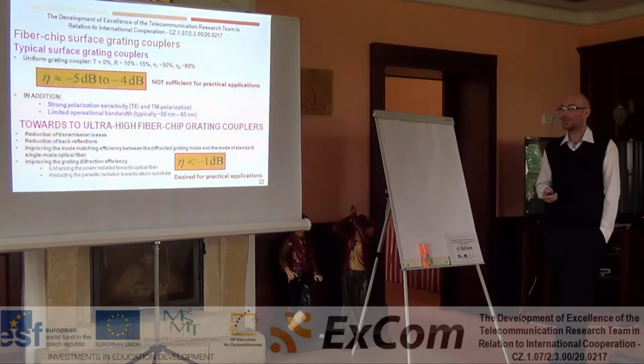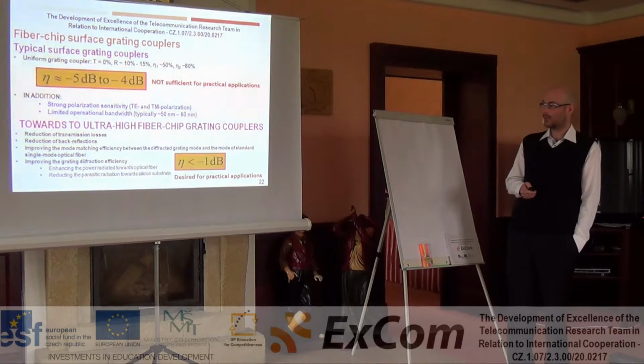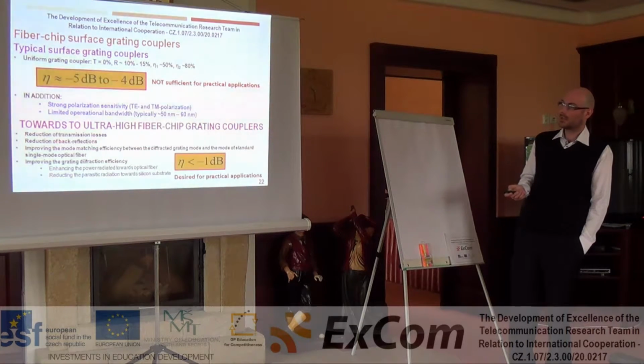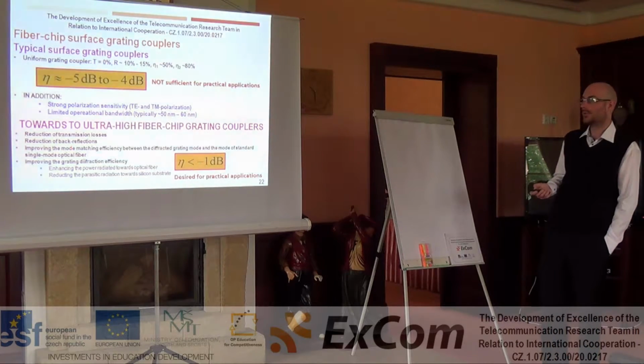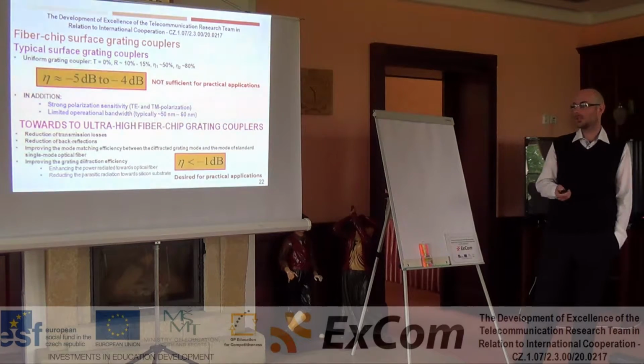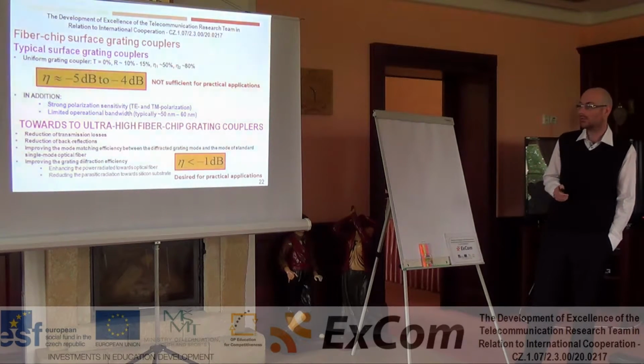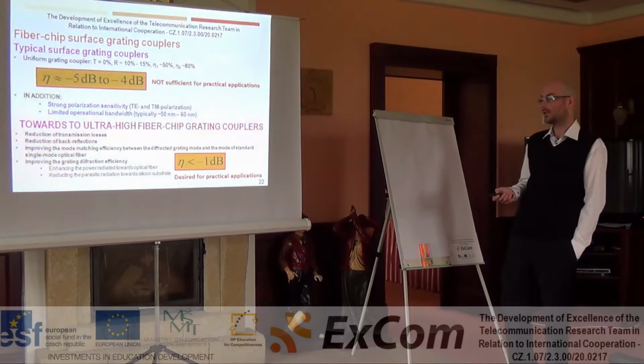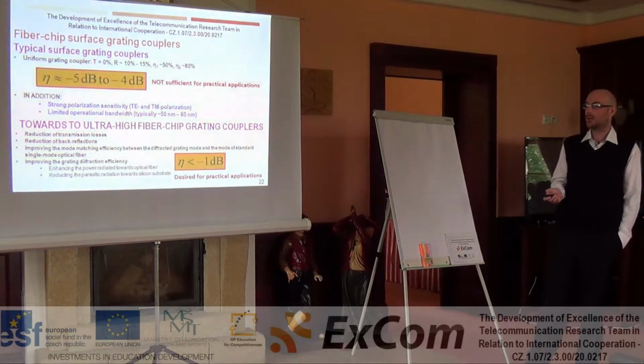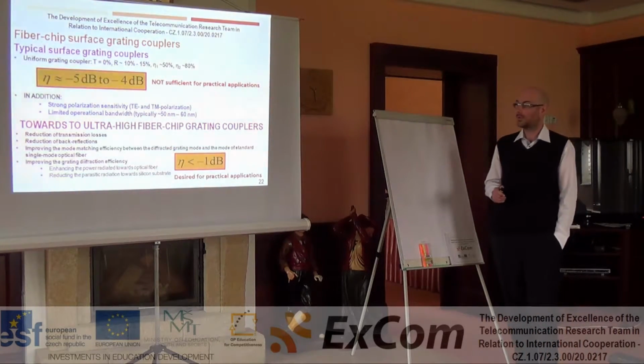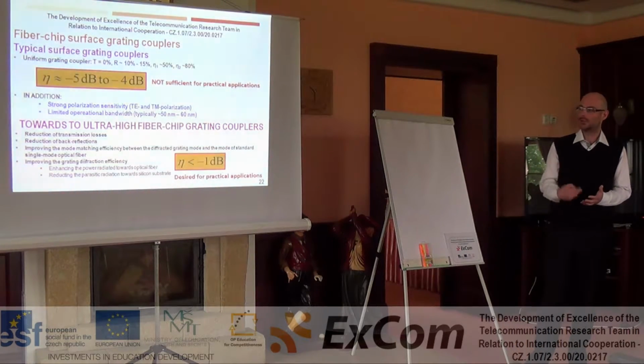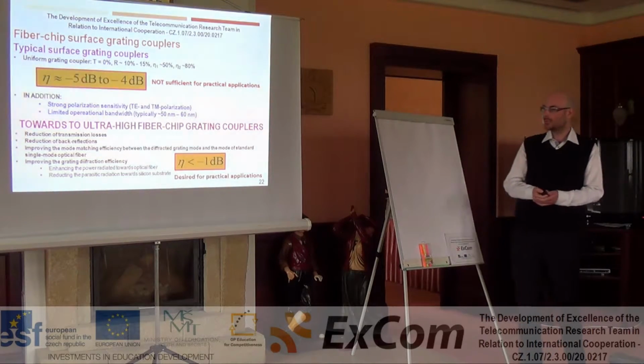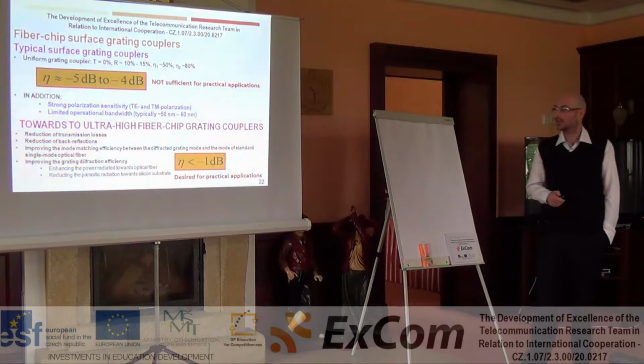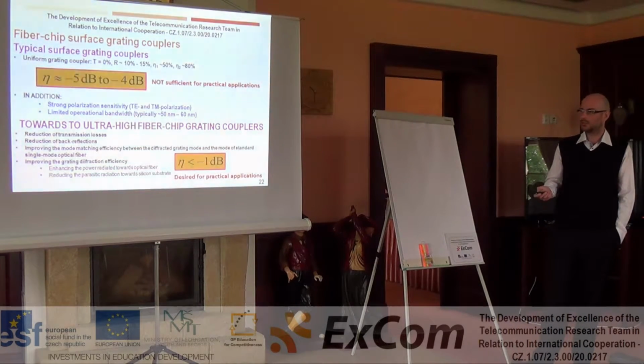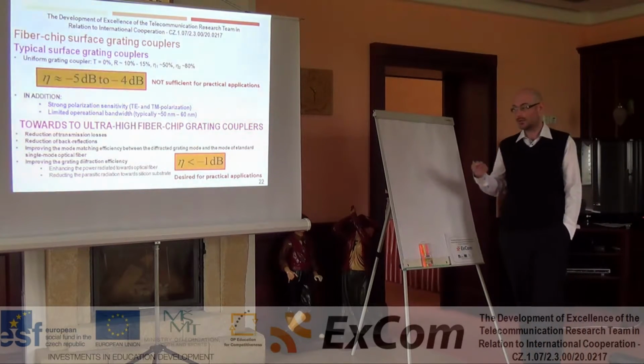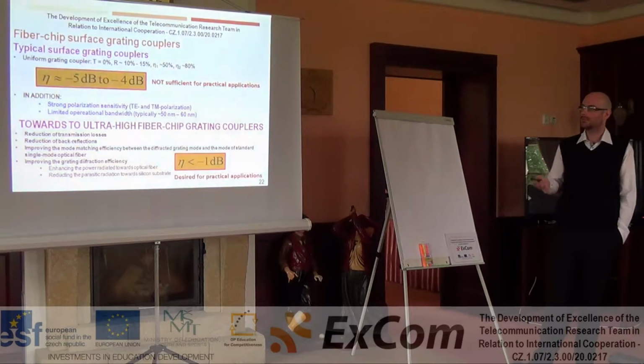There are several ways how we can achieve very high grating coupling efficiency. There is a reduction of transmission losses, reduction of back reflections, improving the mode matching efficiency between the diffracted grating mode and the mode of the standard optical fiber, and improving the grating directionality. That means that we enhance the power that is radiated directly to the optical fiber, or we can reduce parasitic radiation towards the silicon substrate. In principle, we would like to have coupling efficiency that is below 1 dB. This level is considered to be the desired level for practical applications. So,